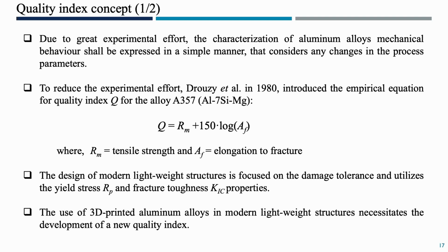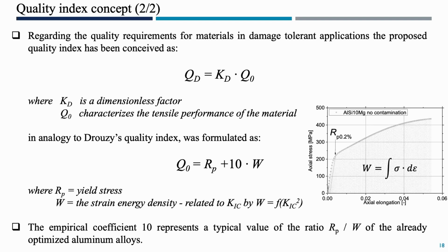Now that I have shown you all the tensile test results regarding the yield stress and the tensile ductility, what is missing, and it is extremely common for cast materials, are some quality indices to denote the overall tensile performance. For example, in the 80s, a researcher called Drouzy from France proposed a quality index, where Q is the quality in terms of mechanical performance, Rm is the ultimate tensile strength and A is the elongation at fracture, and this is a coefficient that comes from expertise.